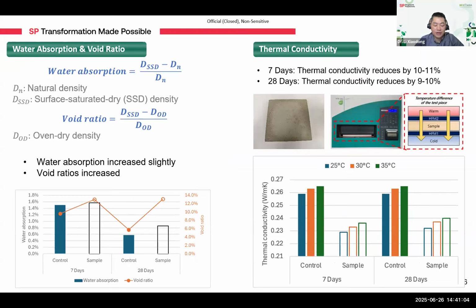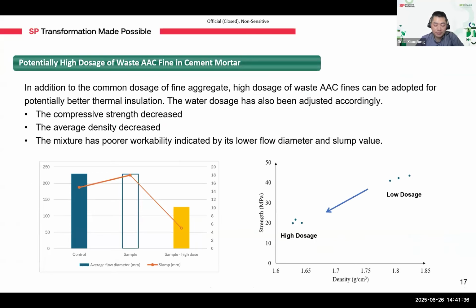So the thermal conductivity was measured using a heat flow meter, which recorded the heat transfer from the hot end to the cold end. Both the water absorption and the void ratio increased slightly, which is expected due to the porous nature of the AAC. But more importantly, the thermal conductivity of the mortar decreased by approximately 10%, indicating improved thermal insulation compared to the standard mix.